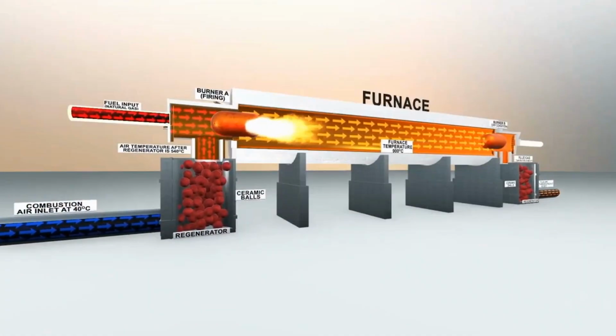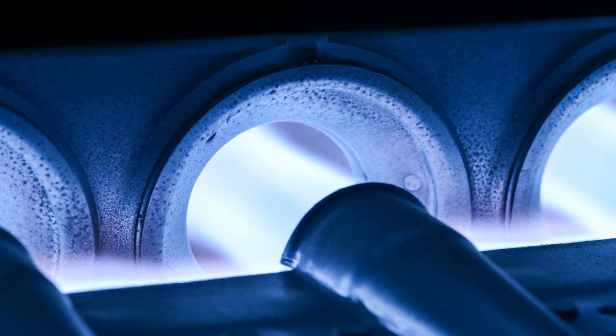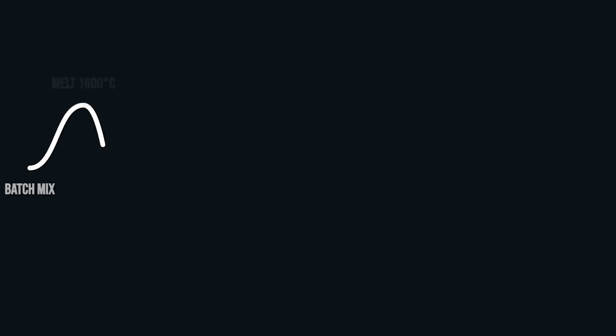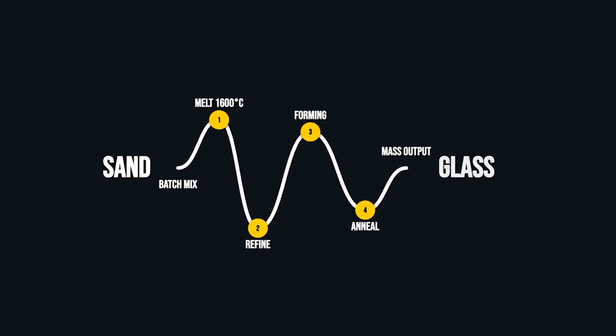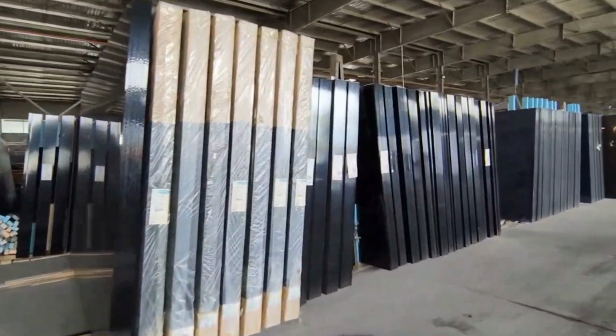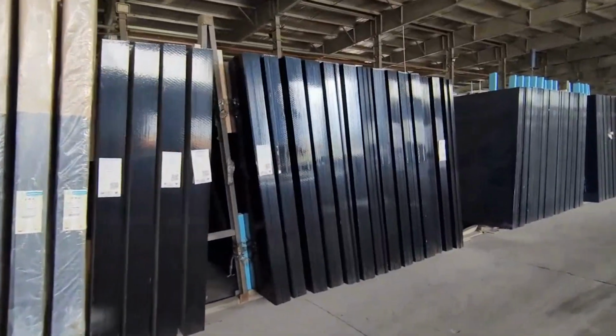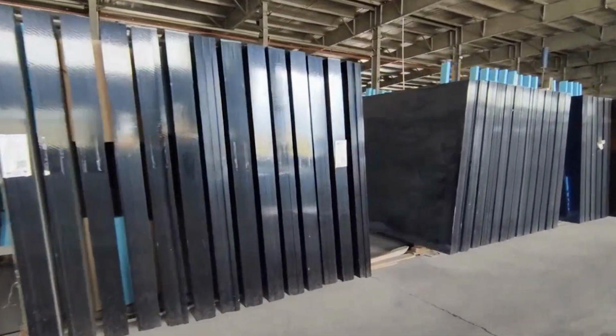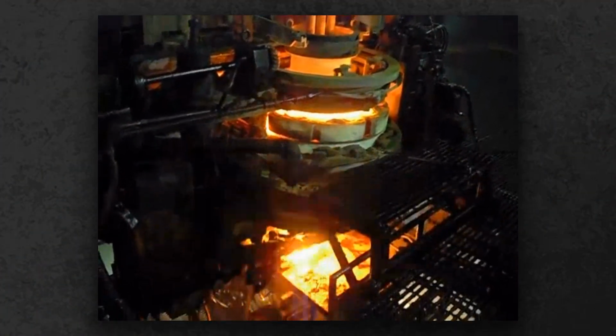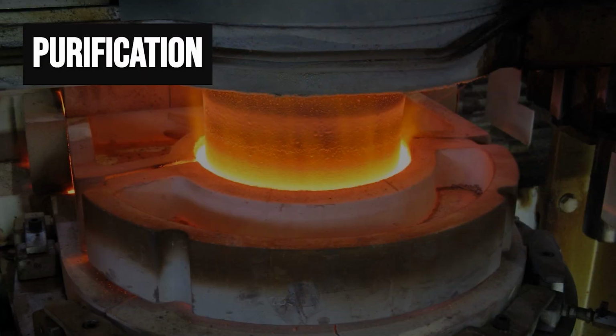Gas and oxygen burners, sometimes aided by electric boosters, maintain the inferno with precision. Any lapse, a blocked burner, a sudden drop in pressure, could threaten the entire operation. The unbroken cycle of melting, 24 hours a day, is what allows megafactories to produce millions of tons of flawless glass every year. Once the raw batch has melted into a river of glowing liquid, the next challenge is purification.